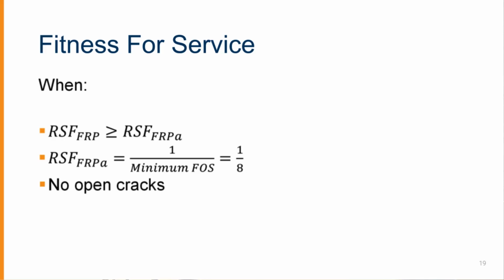Well, the allowable remaining strength factor for FRP is different than it is for steel as given in API 579. The reason it's different is because FRP equipment is designed with very different factors of safety than steel equipment is. So we're actually using an allowable remaining strength factor of basically 1 divided by the minimum factor of safety that we use in construction codes, and that's 8 for most intents and purposes. So it's 0.125. We've actually found from practical experience that this number works.